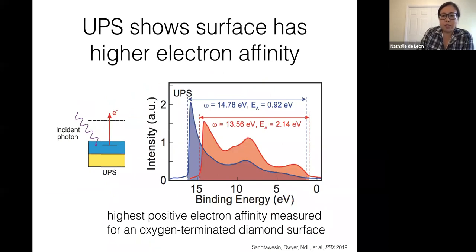The other consequence of this disorder is that if we do ultraviolet photoelectron spectroscopy, which is a probe of the occupied states, what we actually see is this very large difference in the electron affinity between these two different surfaces, which is very surprising because the oxygen coverage is pretty similar.